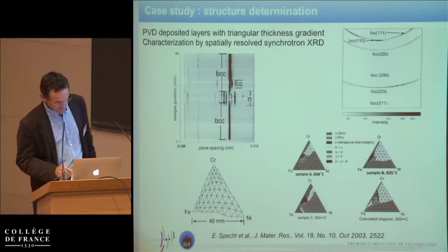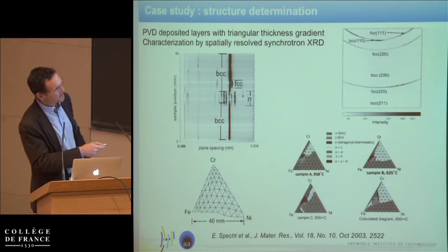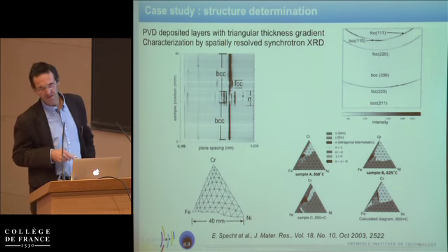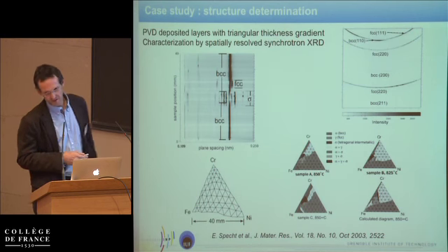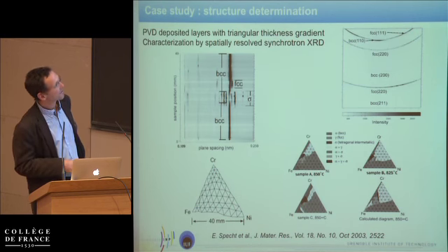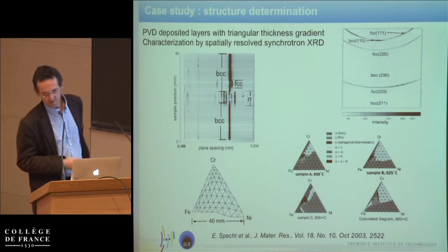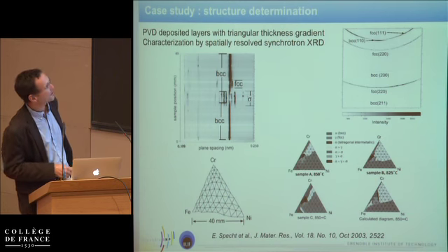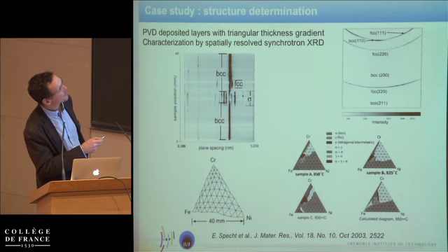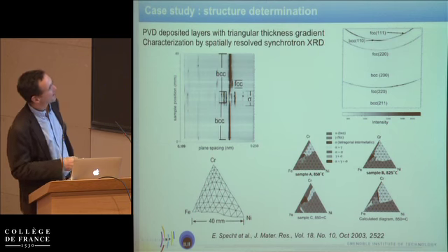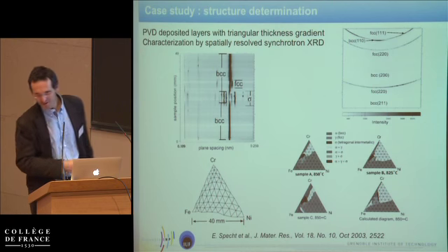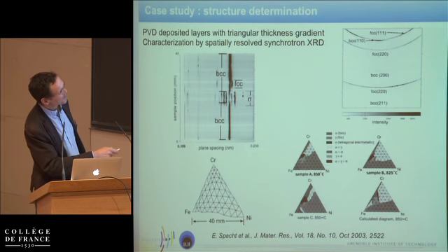Okay, this may be a bit coming back to determining phase diagrams, but just to show the possibility of using X-ray diffraction to map the space of phase structures obtained by diffusion couples. And so here it was a triangle thickness gradient of chromium, iron, nickel deposited by PVD. And then, so it's almost a nice triangle. This is the experimental